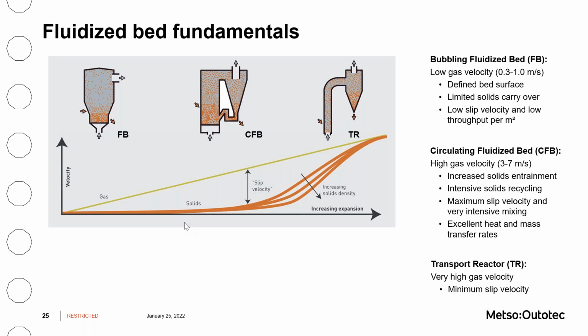In contrast to this, a circulating fluid bed reactor has a high gas velocity with a high solid entrainment and recycling rate. Intensive mixing and excellent heat and mass transfer make it an optimal reactor for fast reactions with short residence time requirements. The transport or flash reactor has a high solid entrainment caused by very high gas velocities. It does best what its name suggests, pneumatically transporting material. As it provides still decent heat transfer rates, we use it as a flash heater in the process. The next slide shows nicely why these reactor types are ideally suited for iron ore reduction under hydrogen.